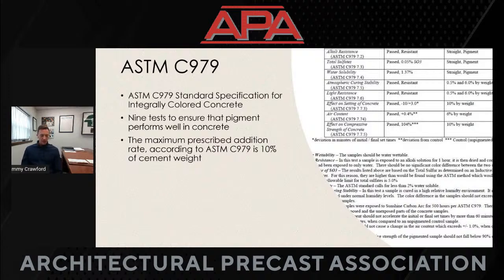ASTM C979. I touched on this earlier. This is the ASTM standard specification for integrally colored concrete. All pigments used in concrete should pass ASTM C979. There are 9 tests that pigments need to pass in order to prove that they can perform well in concrete. The maximum prescribed addition rate, according to ASTM C979, is 10% of your cementitious weight. So basically, that's a fancy way of saying, if you have 100 pounds of cement, don't add more than 10 pounds.